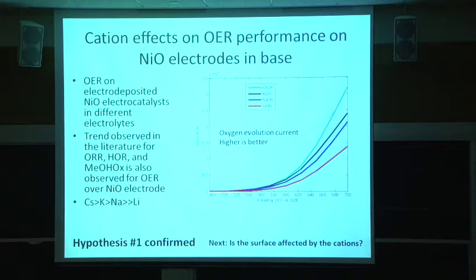All right, and I should point out, these are all reversible. If I take this one and put it in lithium hydroxide, it becomes very bad. If I then switch it back to cesium, it becomes much better. So we can do all of these things reversibly, which makes it very clear it is an electrolyte effect. Okay, so hypothesis 1 confirmed. We can actually promote the oxygen evolution reaction by changing the electrolyte composition.